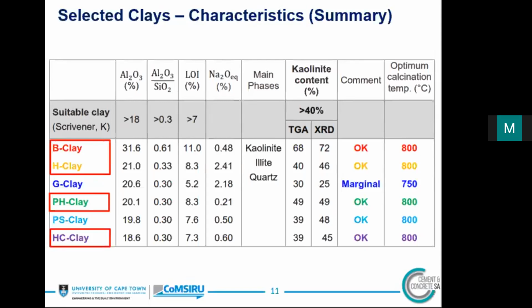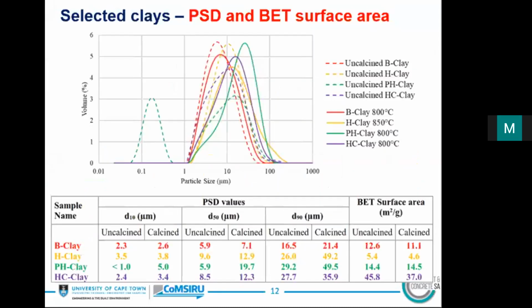Now, something to note here is the equivalent alkalis in the selected clays. You can see the equivalent alkali of the H clay is very high compared to other selected clays. So this will obviously affect the performance of the LC3 mixes with H clay. Now this figure and table down here show the particle size distribution of the selected clays after grinding. Here the target was to achieve D50 less than 10 micron and D90 less than 30 micron before calcination. But during calcination, the particles tend to agglomerate. That's why you have this increase of particle size.